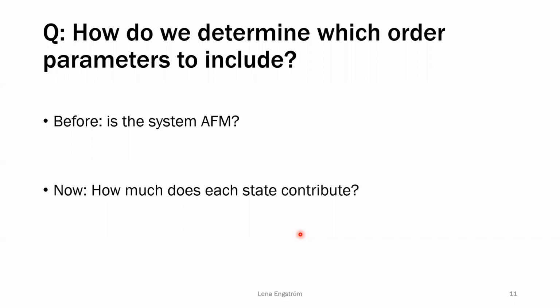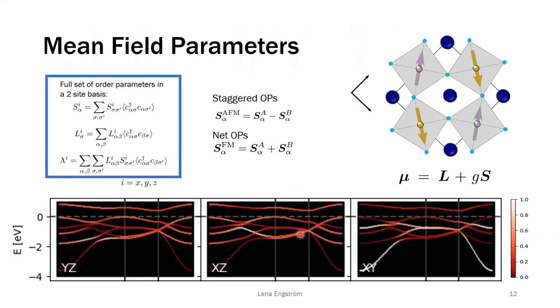Here, if we're considering multiple orbitals and just the magnetic order, is what I'm starting with. We want to ask more: what are the different contributions from the different bands and from the different orbitals to the states that we see, and how can we change that? So what we want to consider is a full magnetic moment, which is what we observe in experiments, which will consist of both the orbital angular momentum and the spin angular momentum, which in this case we can have in all three directions.